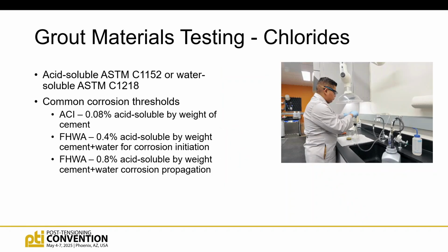We'll also do chloride content analysis. So my default is generally acid-soluble chlorides. That gets all the chlorides out of both aggregates and cement. So it gets you everything. It can result in a little bit higher number than you could get if it was just water-soluble, which is generally what's available to the steel.